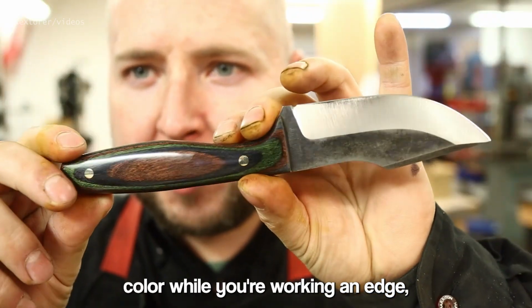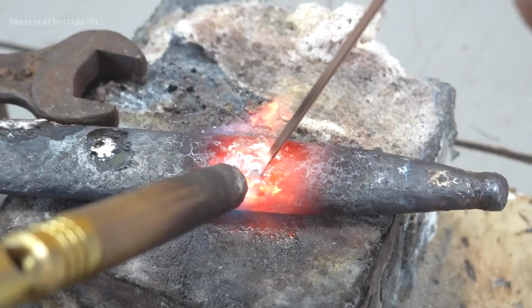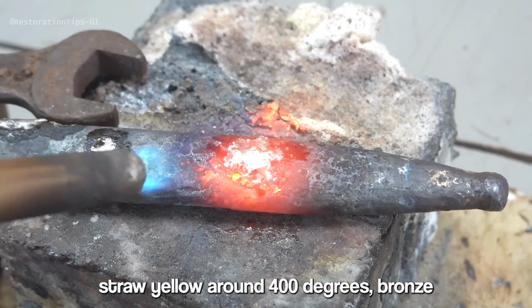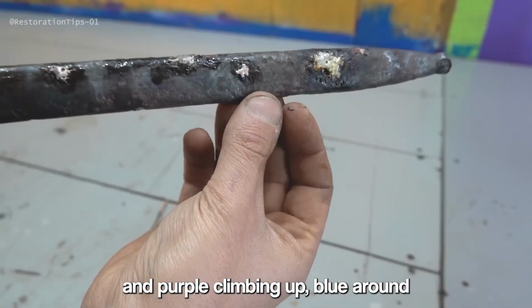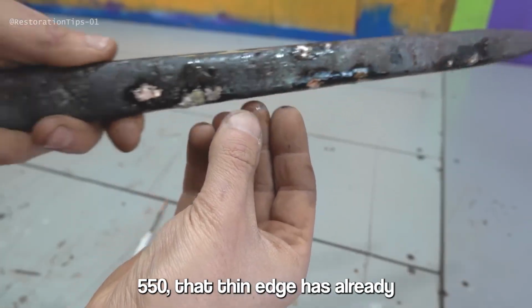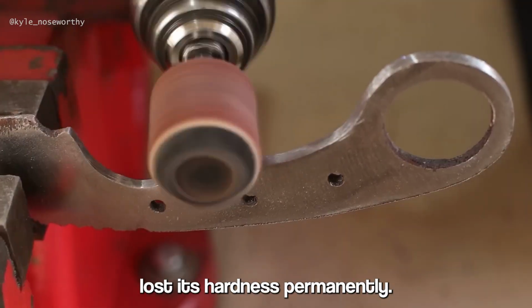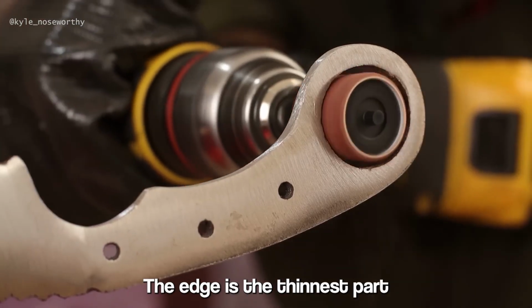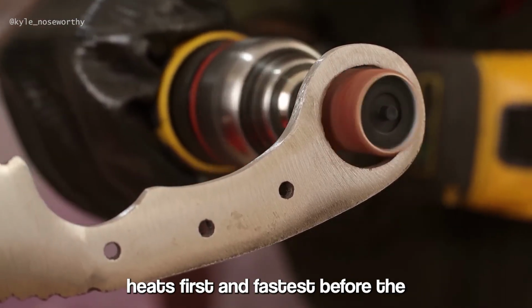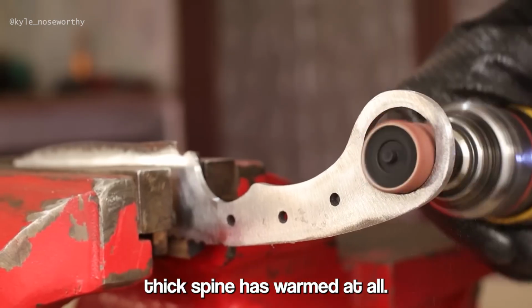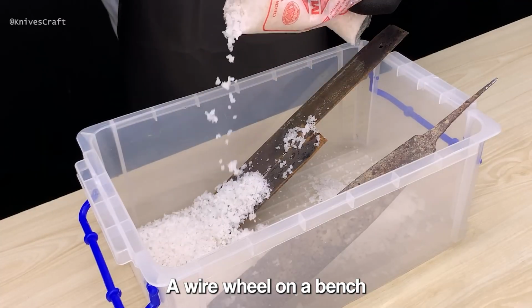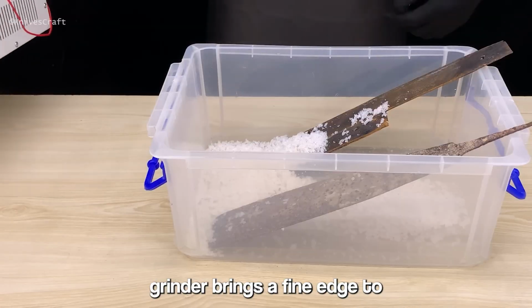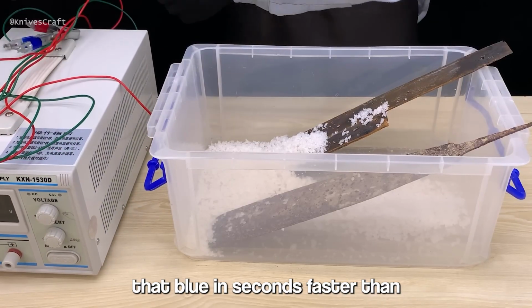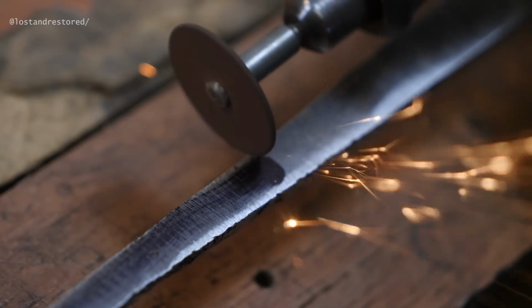If you see the metal change color while you're working an edge, straw yellow around 400 degrees, bronze and purple climbing up, blue around 550. That thin edge has already lost its hardness permanently. The edge is the thinnest part of the whole knife, so it heats first and fastest before the thick spine has warmed at all. A wire wheel on a bench grinder brings a fine edge to that blue in seconds, faster than your eye catches it, so you keep the edge cool.